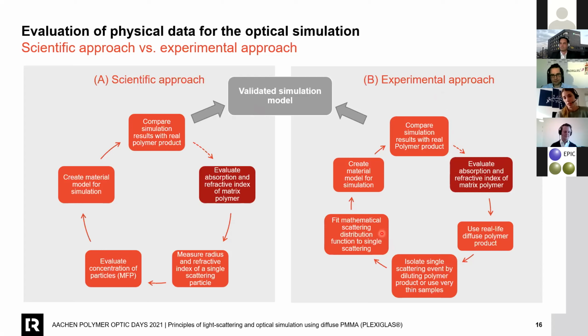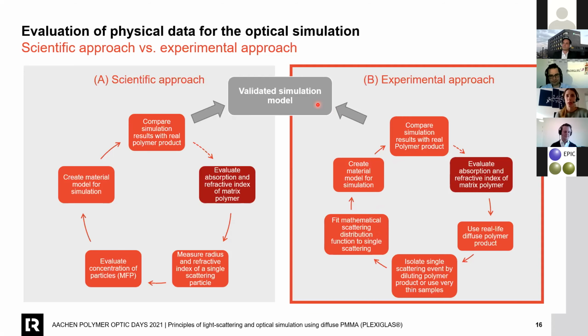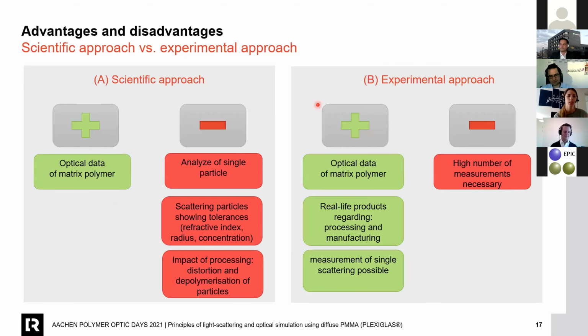If you have this data, you use a mathematical scattering distribution function to fit this to your measured phase function of your single scattering. And the last two steps are the same as in the scientific approach. You create a material model for simulation and compare these results with your measurement. And again, if you have a validated simulation model, you can use this. If not, you have to start from the beginning. We use the experimental approach because for us there are more advantages, as you can see on the next slide.